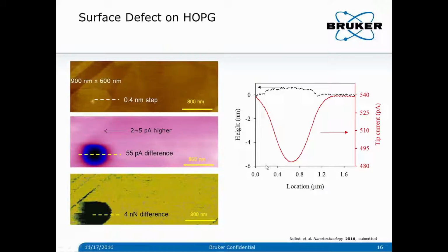Another example related to battery research is the study of HOPG samples, because HOPG is a well-known electrode material, and people would like to use it for lithium-ion battery study as a model system. This study shows an example of a surface defect on an HOPG electrode, and this high-resolution image shows a submicron defect area. This defect area is only about 0.4 nanometer higher than the surface terrace, and this defect results in 55 picoamps, or more than 10%, tip current reduction.